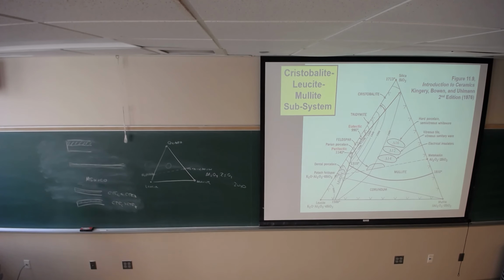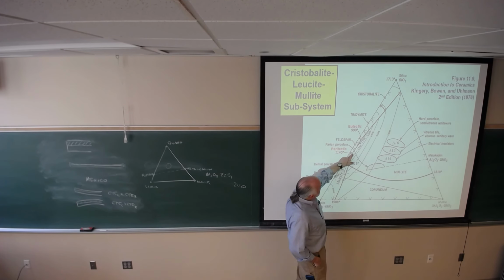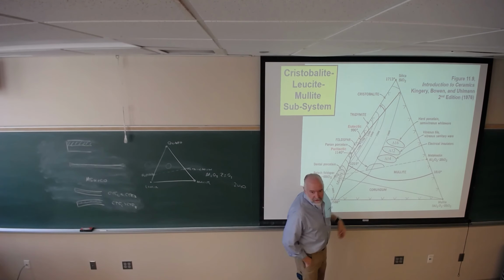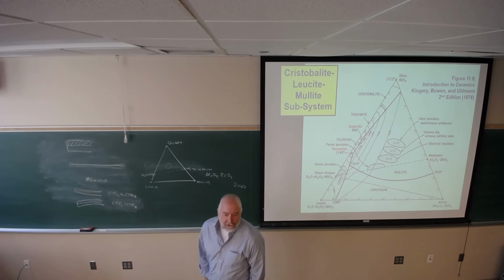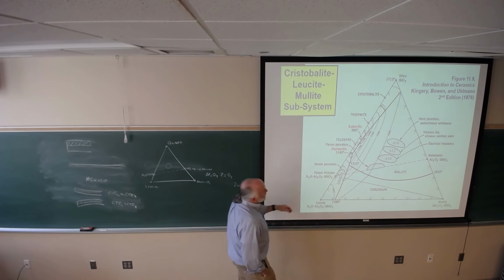What dictates the temperatures? You have a couple things going on here. This is a peritectic at 1140. This is a eutectic at 990. What does it mean to have a eutectic? My God, we're talking about phase diagrams on the very first day for the second time. What does it mean to have a eutectic? Lowest point. Lowest melting point. What's the difference between a peritectic and a eutectic? Okay, so intersection of the phase fields.